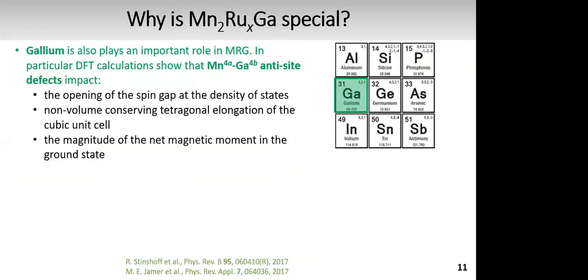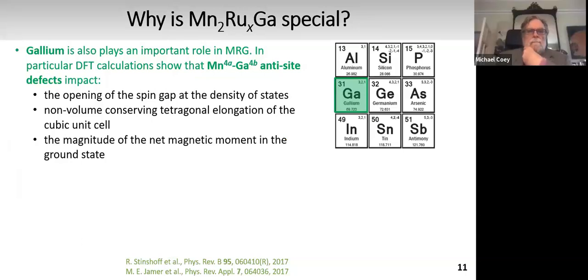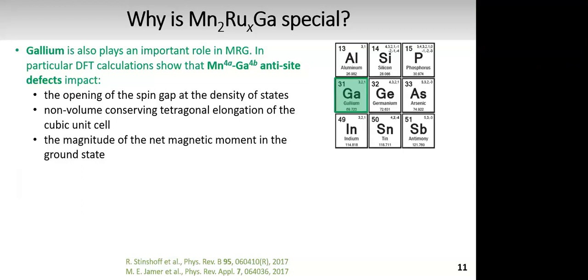Last but not least is gallium, which also plays a very important role in MRG. And the work that was done in the DFT calculations shows that manganese 4A, gallium 4B anti-site defects, those are defects where the two species of atoms basically replace each other in their positions or exchange positions. So those anti-site defects help in the opening of the spin gap at the density of states. They explain the non-volume conserving tetragonal elongation of the cubic unit cell, and they also predict the correct magnitude for the net magnetic moment in the ground state.